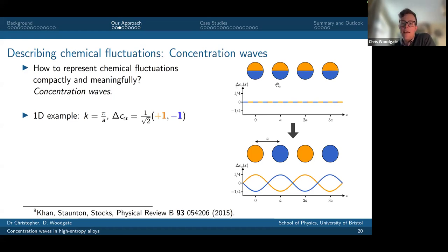Okay, and what I'm imagining is at the top, I start with this situation where all of my lattice sites have a 50-50 probability of being either of chemical species A or chemical species B. And then I'm imposing a chemical fluctuation using a concentration wave, which has wave vector π/a. So it's a wave vector at the Brillouin zone boundary. And it has chemical polarization, delta C alpha. 1 over root 2 is just a normalization factor. +1 means that the concentration of an orange atom is going up. -1 means that the concentration of a blue atom is going down. So when orange is going up, the blue is going down. And then when orange is going down, blue is going up. And this describes this alternating AB ordering. Okay, so that's very nice.